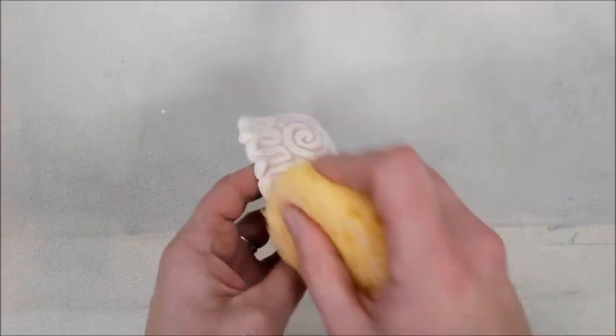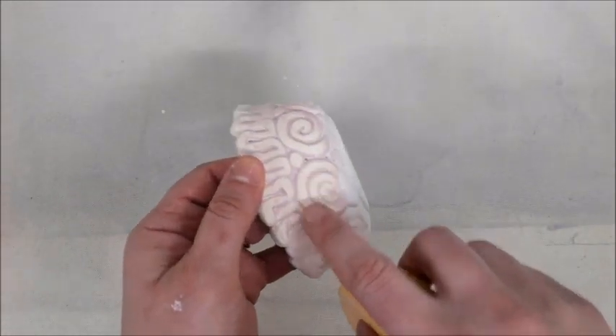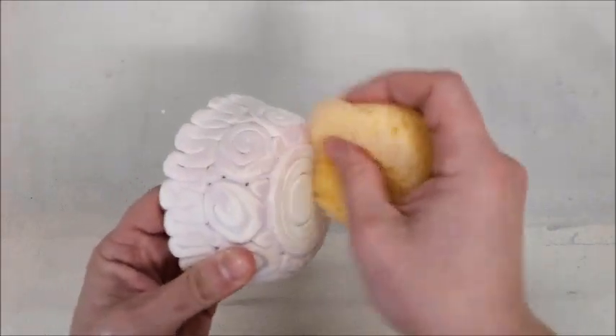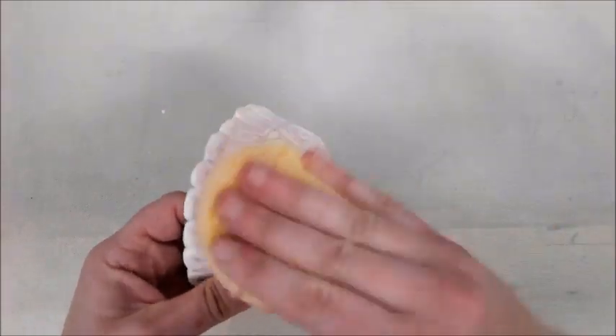What I am going to do now is take a damp — not soaking wet, or you will ruin your project — sponge, and I'm going to lightly brush away the top coat of this clay project. What I am hoping to do is re-reveal the white bisque ware but leave that glaze down inside those cracks. As you can see, a little bit of the white is showing back through but that glaze is still down inside of there. If I do this when my glaze is wet I will not do a good job and it will end up just running.